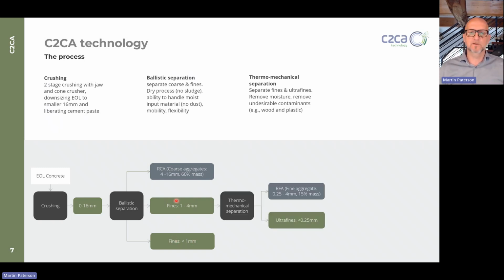The 1 to 4 millimeter goes into the third process step, which is the thermomechanical separation, where we basically have sandstones still having a lot of cementitious paste around them, and we shock heat them, and then the stone expands and cracks off the cement paste. So we get another two material streams out of that: recycled fine aggregates, which is now a very dry and clean sand, and the ultrafines. And the ultrafines and the fines out of the ballistic separator are our feedstock material now to produce our SCM.